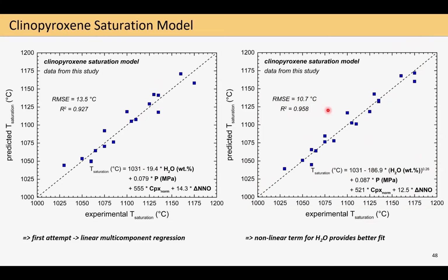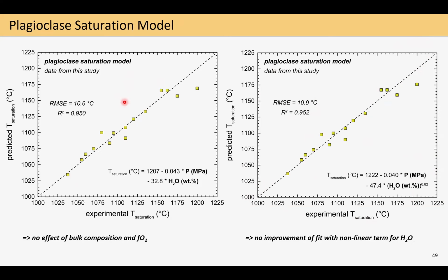Let's now have shortly a look at plagioclase, shown here, where this time I could not observe, linearly or generally, an effect of bulk system composition and fO2 on plagioclase saturation. But here, which is quite remarkable, I think, is that although I tried again with a linear and a non-linear water term, this time both models are performing equally well. So the errors and the R-squares are more or less identical. And it seems like apparently water contents do not affect plagioclase saturation in a non-linear way.